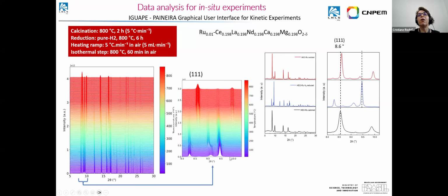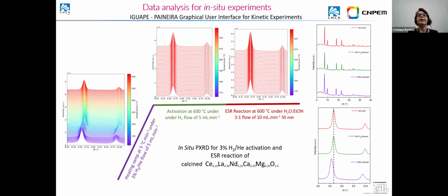Doing a zoom, the user could see all these peaks forming that are telling him that a new crystalline phase was formed, and here it's possible to know when it starts forming a new phase in terms of temperature or time, or depending on the gas that is flowing through the sample. Here is another picture, because after preparing that sample and creating a new crystalline phase, it was applied to a catalytic reaction.